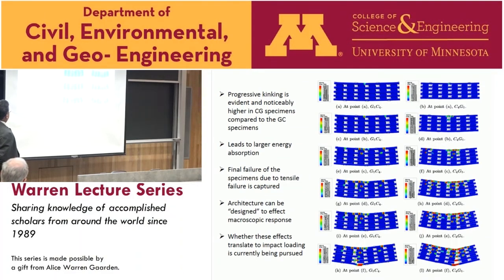Final failure when you have tensile rupture of the tows. Carbon tensile rupture occurs much easier, glass not as easy. So the bottom line, you can design the architecture, right? This model is showing that it can capture the events of the experiments we conducted, which provides us confidence now to start messing around with the architecture to see if I change different layers and different architectures, how I control my overall stiffness and the progression of failure.